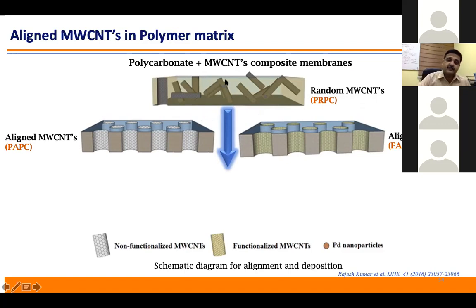But please remember, this is the random orientation. Then what we did, we applied some magnetic field, and we put our Petri dish in between this magnetic field. Once the solvent is evaporated, we removed it. Since it is in the solid state, it cannot go left and right. And most of the CNTs are aligned perpendicular in the polymer matrix. So these are the aligned multi-wall carbon nanotubes in a polymer.